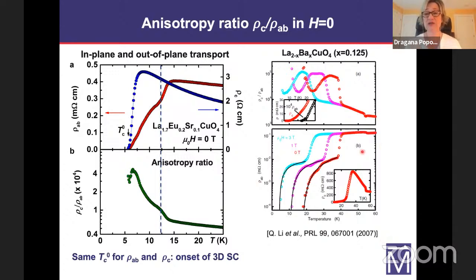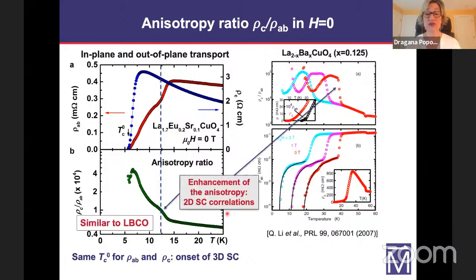Here, the in-plane resistivity is shown on a log scale, so you can see the initial drop maybe more clearly, followed by the final drop of resistivity. And on the top, this is the anisotropy, again, on a log scale. So this enhancement of the anisotropy, this initial bump, is really related to this drop of the resistivity, which is understood, at least in LBCO, to represent the onset of superconducting correlations in the planes. So we conclude that probably the same physics is taking place in our two materials.